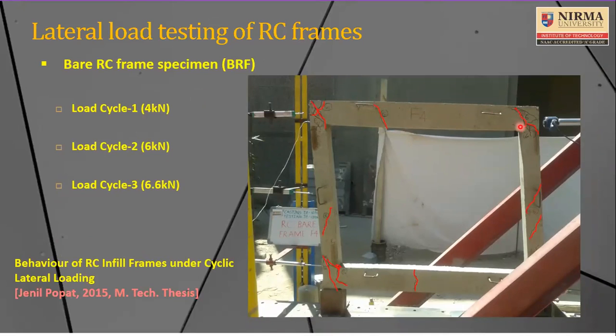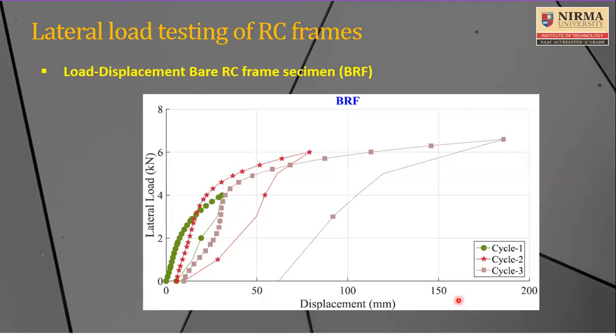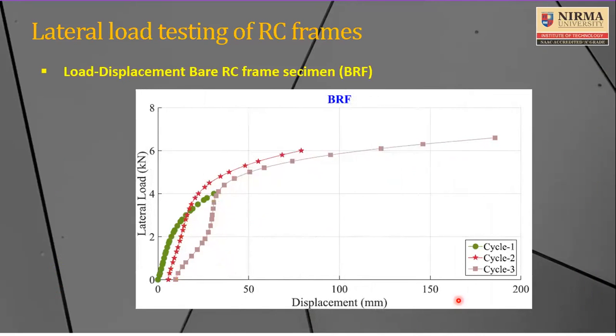So these are some of the photographs, and different cycles have been applied, and you can see the kind of failure that has been observed in the bare RC frame because of the flexure, and the column is undergoing tension and compression. The beam is also undergoing tension and compression, and some of the shear failure you can also see. And then this is the cycle by cycle lateral load versus displacement.